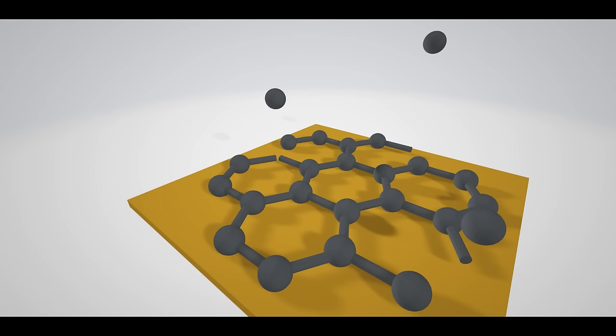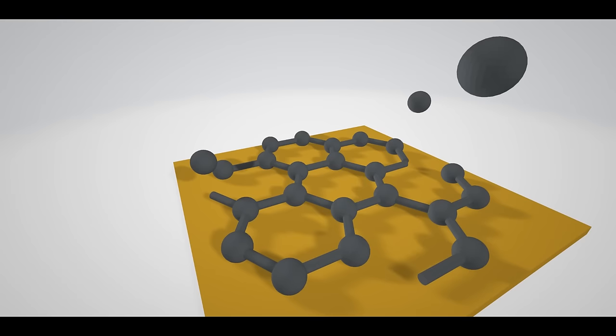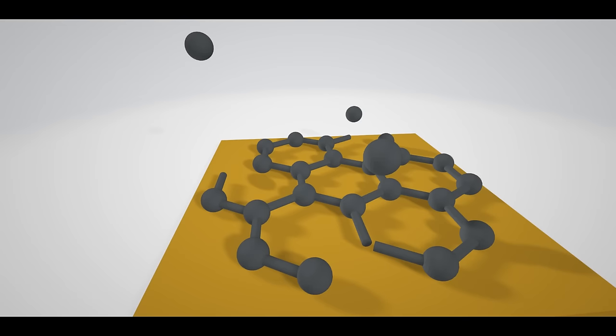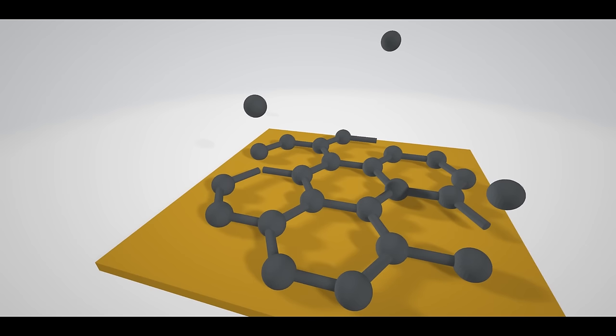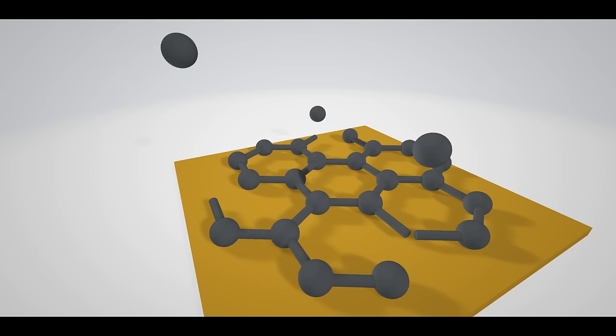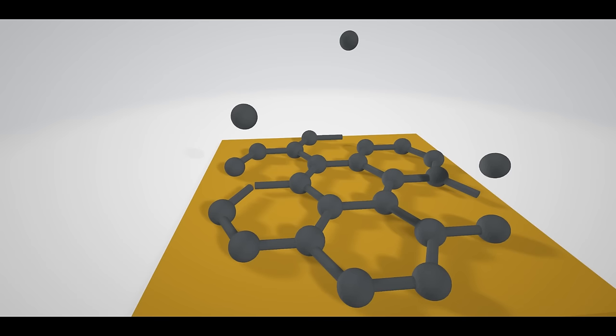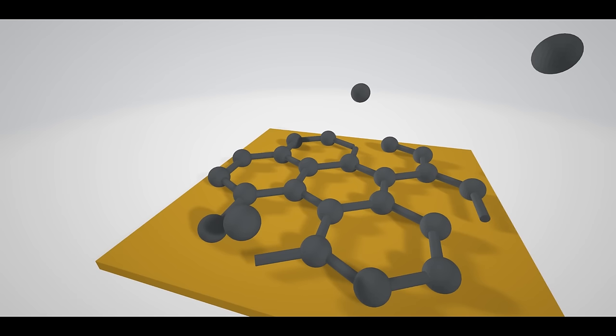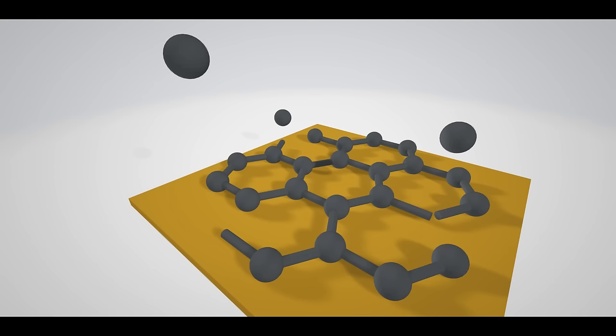Graphene is a two-dimensional crystal, and like other crystals, the best way to build it is to grow it. In other words, it's too difficult to physically build a crystal atom by atom. Instead, you provide the right environment and materials, and the crystal will build itself atom by atom. The way this is done with graphene is to heat a copper plate in a chamber filled with gas, such as methane. The methane gives up its carbon atoms to the copper plate, and in the process, the graphene self-assembles on the copper plate. This is called chemical vapor deposition, or CVD, and that's the easy part.